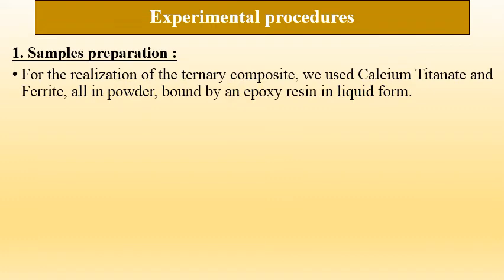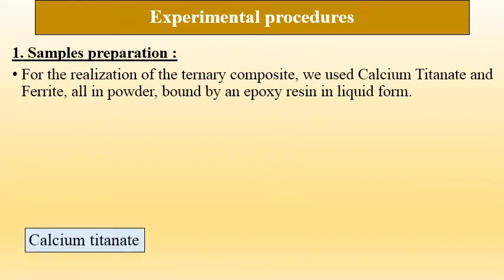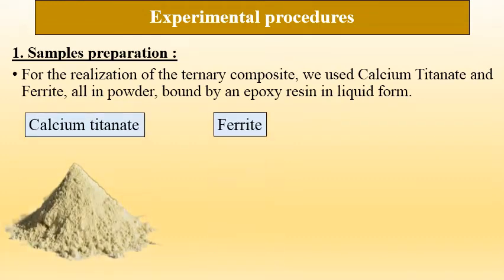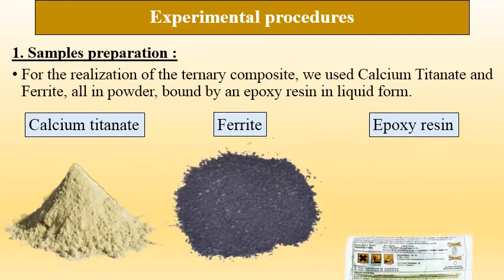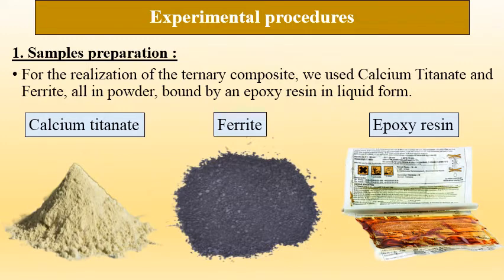Now we move to the experimental procedures. First, we talk about sample preparation. For the realization of ternary composites, we used calcium titanate and ferrite, all in powder, bound by an epoxy resin in liquid form. In this context, we have prepared several samples with different volume fractions. It should be noted that the proportion of the epoxy resin is fixed at 70% in all composites. Consequently, the proportion of the other inclusions, calcium titanate and ferrite, varies between 0 and 30%.